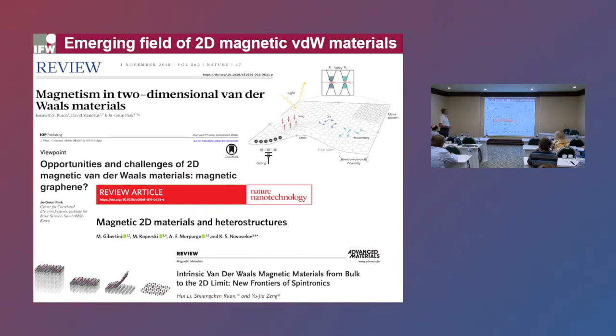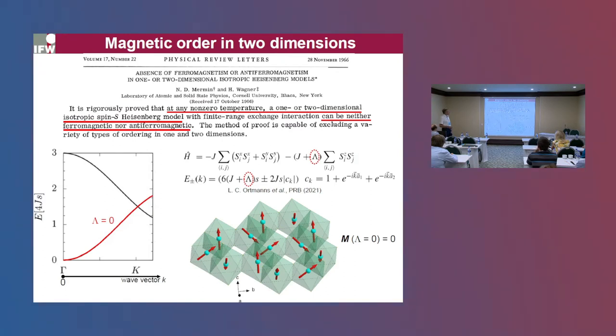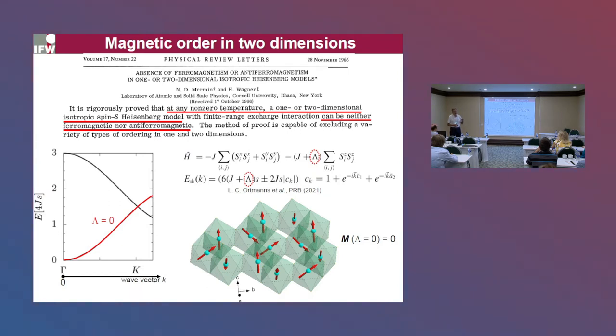The most important property of a single layer should be that it retains magnetic order. This confronts the famous Mermin-Wagner theorem, rigorously proved in the middle of the last century, which states that at any non-zero temperature a one- or two-dimensional isotropic Heisenberg spin model can be neither ferromagnetic nor anti-ferromagnetic. As soon as temperature is raised above absolute zero, low-energy spin waves are excited in the system, and long-range order is destroyed in the two-dimensional limit.